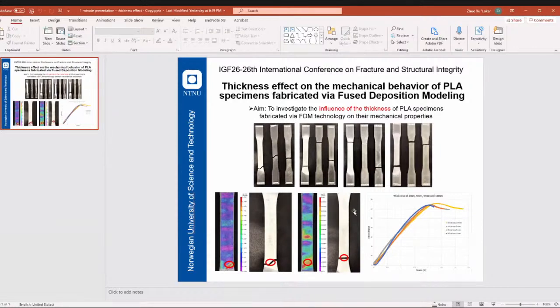So in this research, we have set 4 different thicknesses, which are 1 millimeter, 3 millimeters, 5 millimeters, and 10 millimeters. All of them have the same gauge length and other parameters except for the difference of the thickness. For the standard specimen, it's 3 millimeter thickness, and all of them are tensile specimens. So we did a tensile test for all of them.